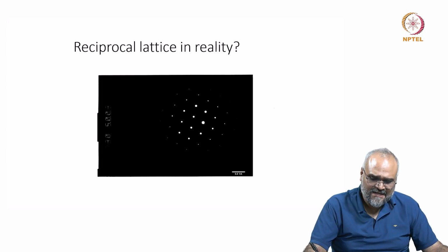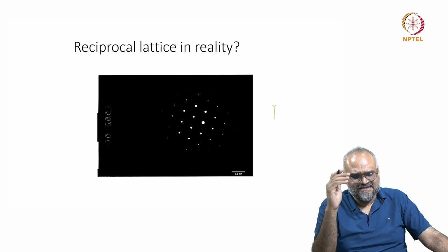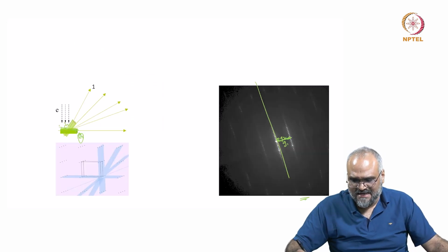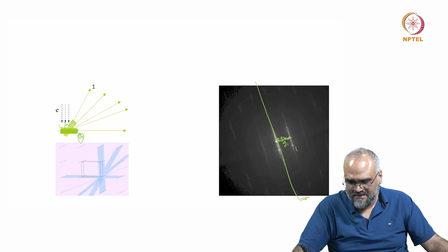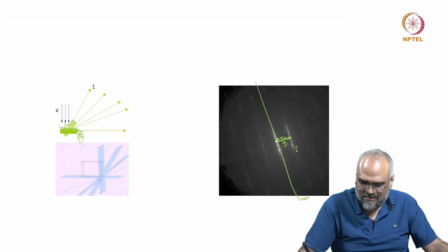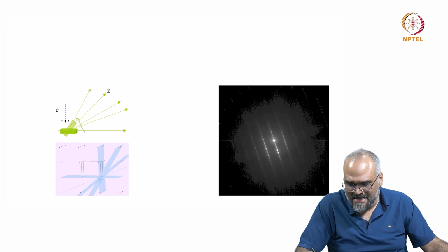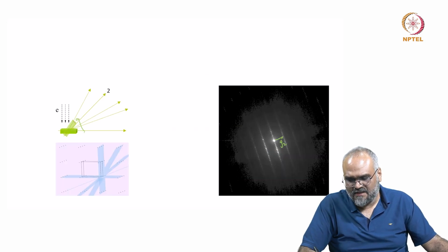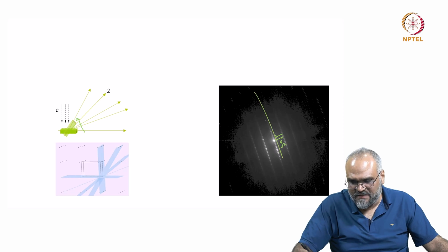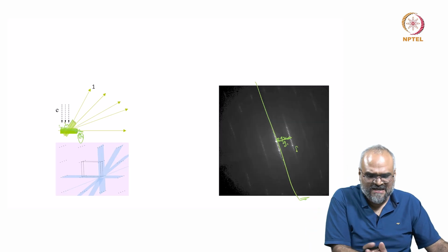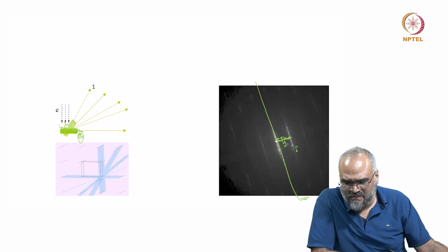let us say I maintain one particular tilt axis as constant. So, for example, in these three systems, I had this long axis or this D1 or this G1 as constant. I am changing this G2 value here. So, I actually see the gap between these planes becoming narrower as I orient my sample along different crystallographic planes.